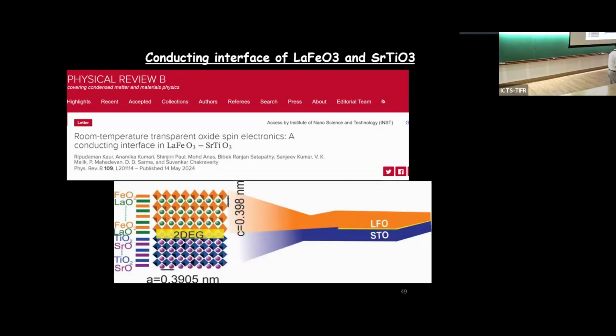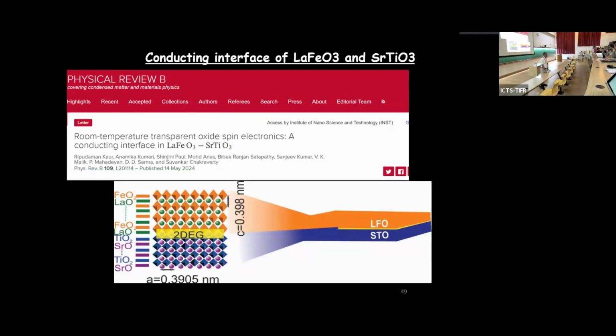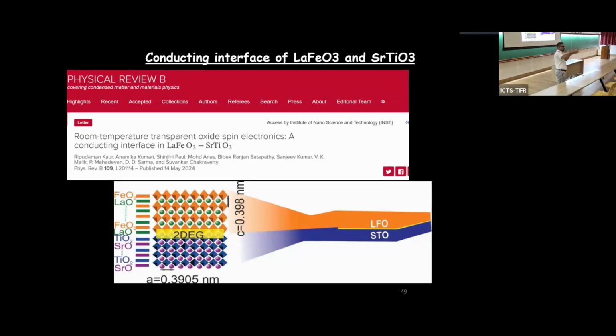So one small question. Please. Where you are comparing the fluence in that slide, what about the film thickness? Are the film thicknesses the same for all the samples? We keep the film thickness the same by changing the deposition time. And in that paper also we have shown the reflectivity. We could see it for almost all, and it was very easy for us to judge the thickness. Of course, there is a plus minus few nanometer difference.